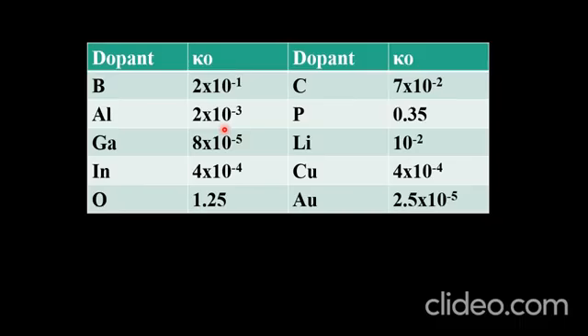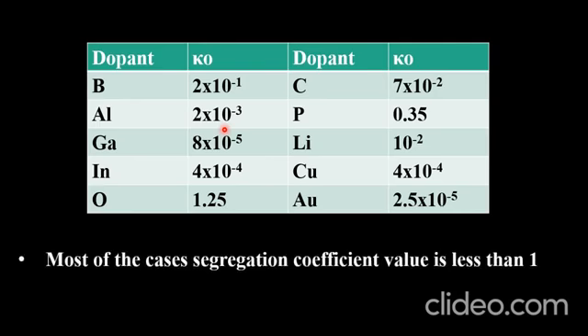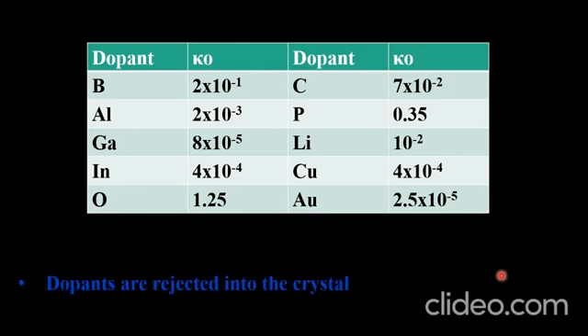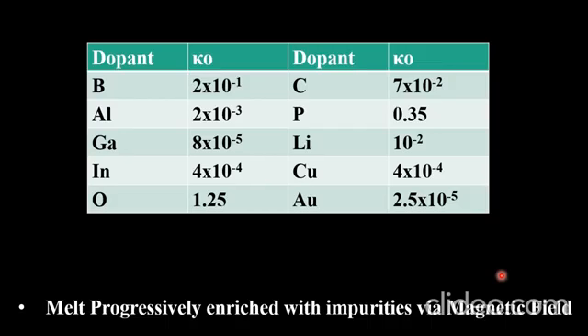So that's why different types of magnetic fields or different types of setups are introduced to incorporate dopant inside the single crystal. In most cases, as you see here in the table, the segregation coefficient is less than 1. So the single crystal does not favor incorporating the dopant inside it, and the dopants are basically rejected from the single crystal structure. That's why, most commonly, a magnetic field is used to introduce a dopant inside a single crystal. So the melt is progressively enriched with impurities via the magnetic field.